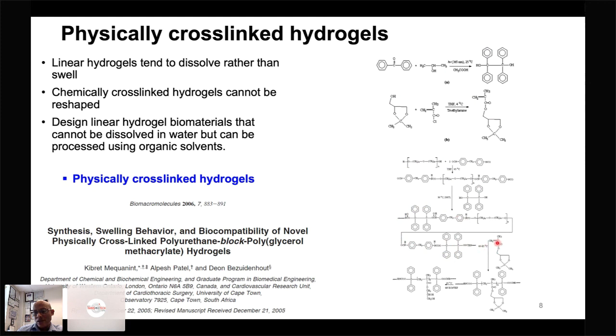Then we took the solketal methacrylate monomer in here, and then we were able to create this block polymer. So this bond breaks down, and then it forms a radical, and then it inserts this monomer. And so you can see that you can basically produce n repeat units of this solketal methacrylate in the polyurethane backbone. Now you can hydrolyze that, which is what we did, and then at 25 degrees Celsius and in the presence of reagents, in this case hydrochloric acid, you can actually hydrolyze these groups. That gives you glycerol methacrylate, which is the title of the paper. So this is a poly glycerol methacrylate block polyurethane hydrogel material.